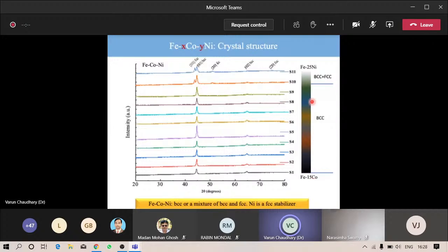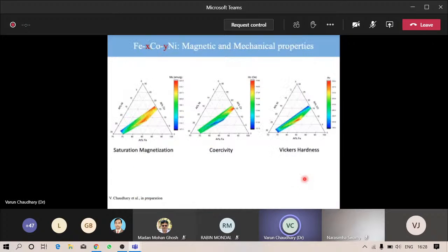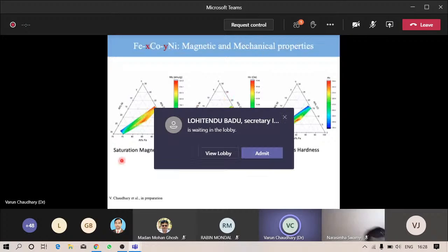For the nickel-rich side, we have a body-centered cubic plus face-centered cubic structure, while on the cobalt-rich side, we have a body-centered cubic structure. So we can say that nickel is a face-centered cubic stabilizer in this system. And here are the magnetic and mechanical properties for these samples, such as contour graphs for saturation magnetization, coercivity, and then we got hardness.